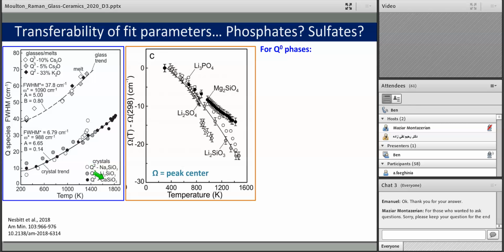Again, sodium, lithium, calcium. For the glasses on top, there's cesium or potassium. This tells us that the broadening due to temperature can be accounted for just by having your width be constrained in the glass by that of the band in the crystal at its melting point, which is for Q0 species around 40 wave numbers, and it increases from there.